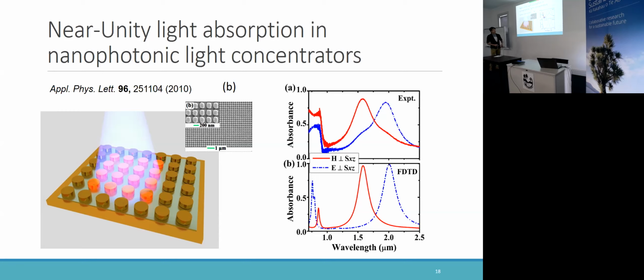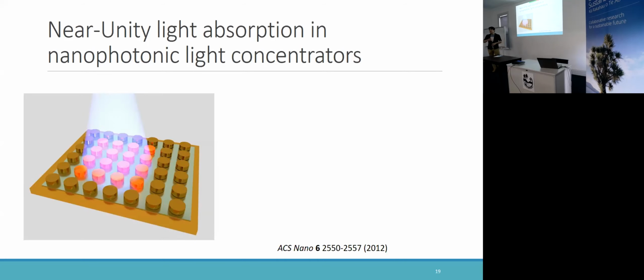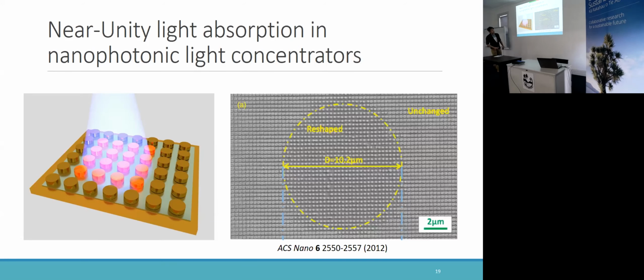So we already know that these gap resonators are very good light absorbers. But then we have to ask, where did the absorbed light energy go? Here I'm going to show you one experiment. We shine a laser beam onto the structure and gradually increase the laser power. When the laser power reaches some value, I forgot the value, but it doesn't matter, we can see the shape of the nanoparticles inside the illumination area has been significantly modified.